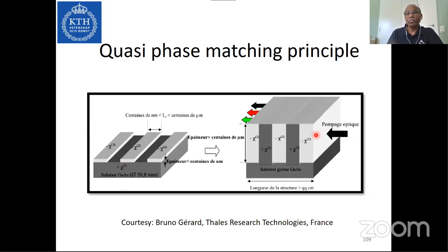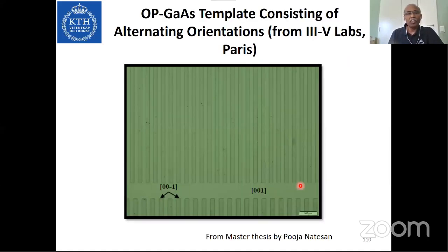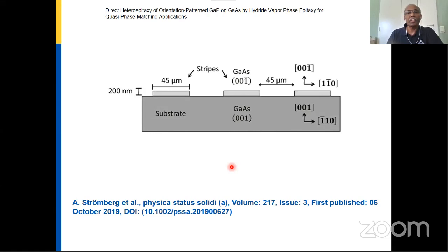Then when you pump with a laser, you will have 3 wavelengths, pump, idler and signal, and you can optimize the periodicity and the pumping wavelength, and you can obtain entangled photons from the photons which come out. This is the top view of this structure. And this is the cross-section view of the structure. In this direction you have the 0, 0, -1 direction here, whereas here is the 0, 0, 1 direction. Okay, so it is inverted.